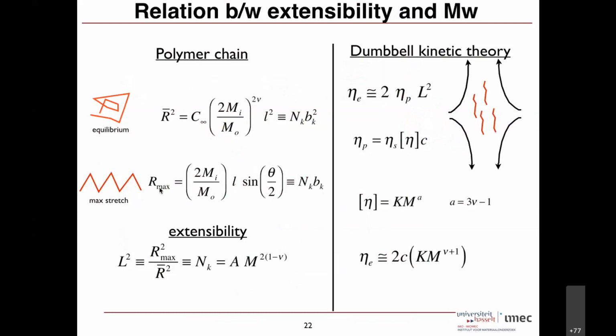And then, using these two parameters, you can define something called extensibility. And that extensibility will give you some kind of a parameter, molecular weight to the power of this nu. This nu is nothing but solvent quality. Does the polymer like the solvent? If it likes the solvent, then it opens up. If it does not like the solvent, then it will be like this. Right? So it's basically like that. And then there's something called dumbbell kinetic theory. From that, you can also calculate something called extensional viscosity that depends on the polymer viscosity and this extensibility factor.